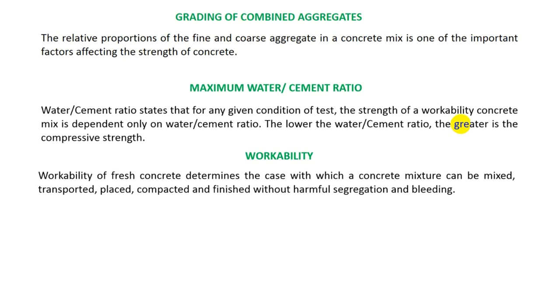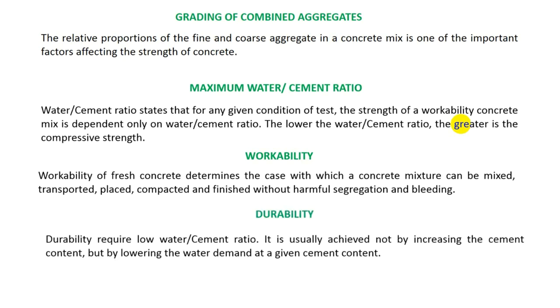Durability requires a low water cement ratio. It is usually achieved not by increasing the cement content, but by lowering the water demand at a given cement content. The durability is not improved by simply increasing cement content. Even though cement is a strong binding material, using more cement is not the solution — the solution is to maintain the minimum water demand required.